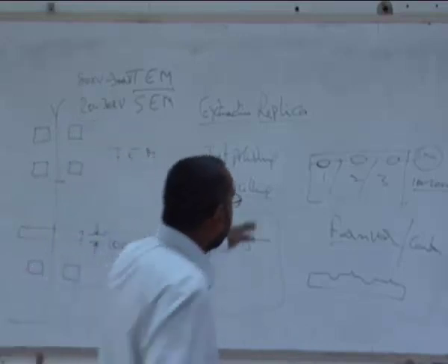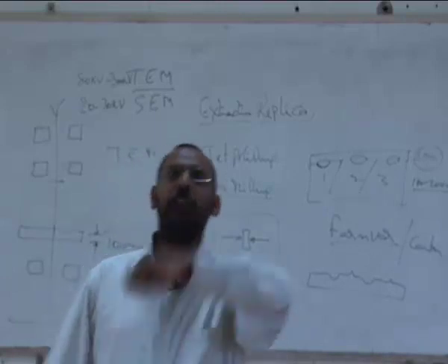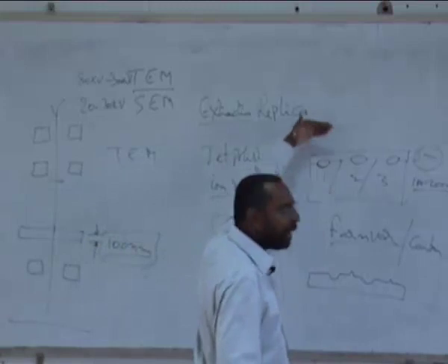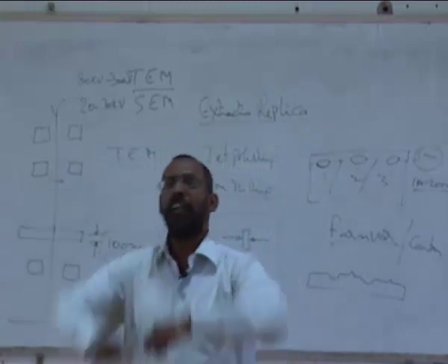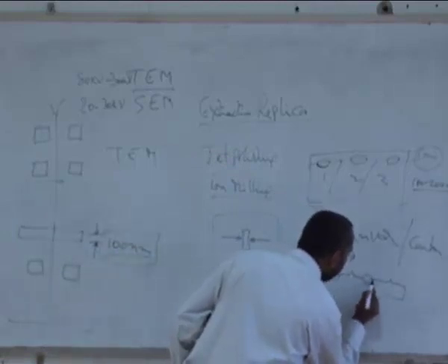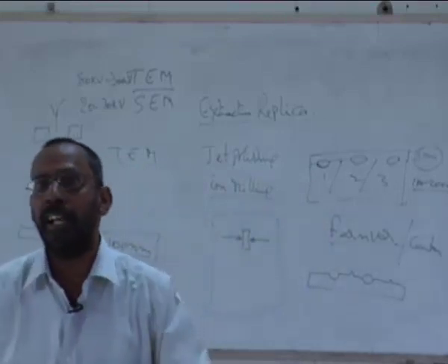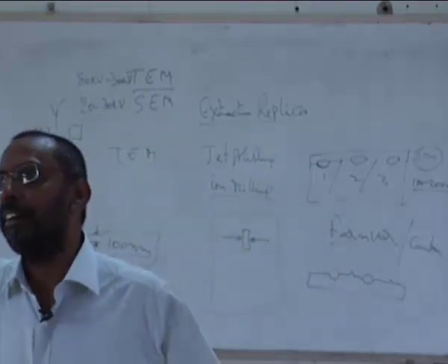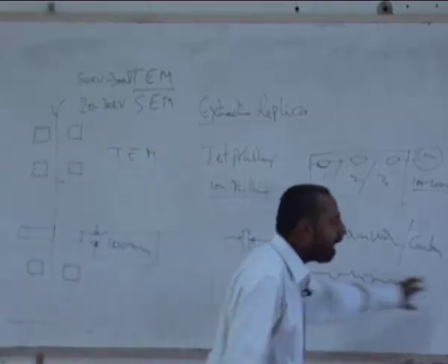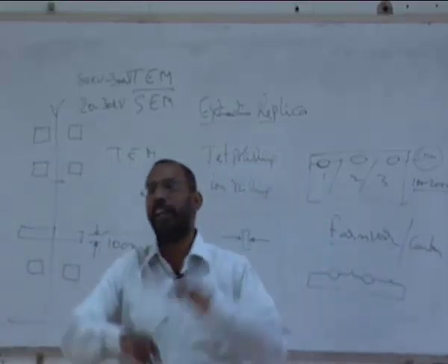Now if you deposit your carbon film or formvar film and try to pull it off, there is a probability that these loose particles may get embedded into that formvar film and come out. So when you look at it, you may possibly find a particle embedded into it, one or some of these particles. Now you are not just seeing the carbon, but carbon into which these particles got embedded.